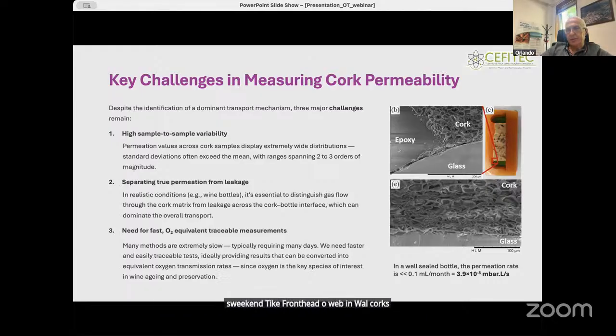However, in wine cork stoppers the data is better, since the cells are compressed and the values span fewer orders of magnitude. But in that case, we believe that the measurements we make in wine cork stoppers are due to leaks, not to true permeation. The interface between glass and cork is very tricky, is very rough. Cork is rough, although flexible, and it is the flexibility that gives the tightness, the sealing capacity. For liquids it is easy, but for gases it is more difficult, and some routes can remain open through.